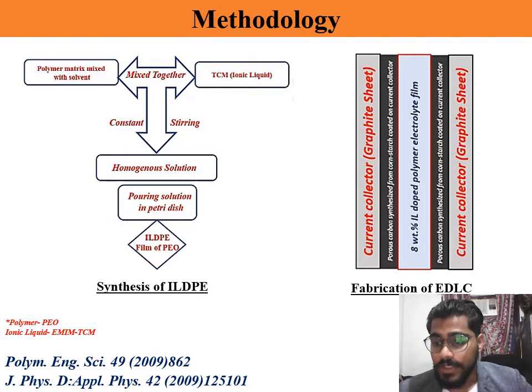The Teflon petri dishes were cleaned efficiently, and different weight percents of the ionic liquid doped polymer electrolyte solution were poured into different petri dishes, at 1 to 10 weight percent. The polymer electrolyte solutions were kept at room temperature for 5 to 6 days for the complete removal of the solvent to get a freestanding solid polymer electrolyte film. Next, in the schematic, you can see that the electrical double layer supercapacitor was fabricated using graphite sheets as a current collector.